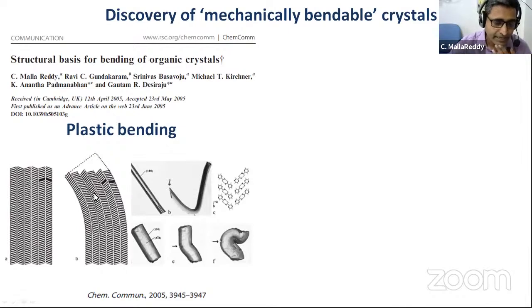We tried to understand what was going on here. Initially we got one or two examples. Then later we did a survey, and got about 10 different crystals, totally different compounds, with exactly the same bending property. I looked at the crystal structures and found that all these crystals have weak interactions, more or less like van der Waals interactions. Most of the time you have stacked columns, with relatively stronger interactions within the columns and relatively weaker interactions between the columns. Because of this, the layers in the crystal could easily slide one over the other, and that would lead to this bending deflection.